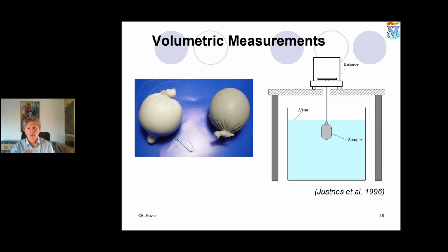Then, how to measure this volume reduction? This volume reduction is measured by using a so-called condom test. Yes, this is a very popular test in the labs. We have to fill this condom with cement paste, for example. Or by the way, there are big condoms, I'm serious, which are used for horses, for example. Yes, I saw these condoms in the labs for measuring volume changes in concrete or mortar specimens.